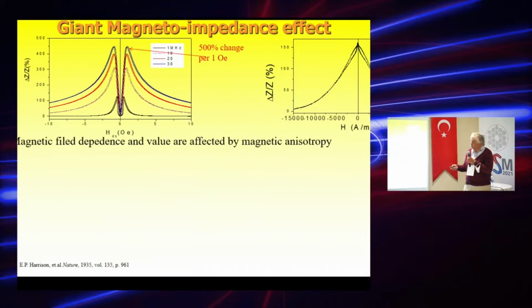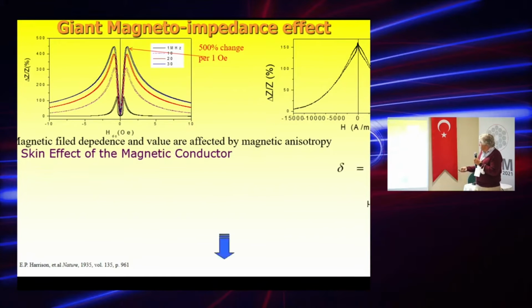Larissa already mentioned the magnetic impedance effect. It can be quite high in this kind of materials, up to, in this case, about 500%, but it could be even higher. The origin of this effect is the skin effect of a magnetic conductor. Generally speaking, the penetration depth, the skin depth, depends on magnetic permeability. Therefore, soft magnetic materials are essentially important for this kind of application.